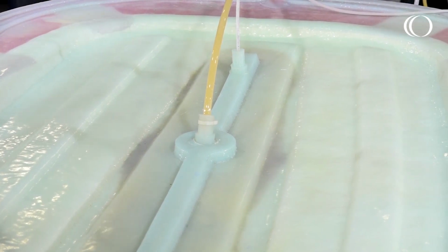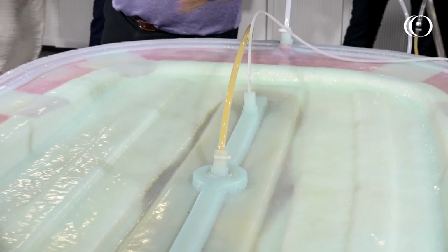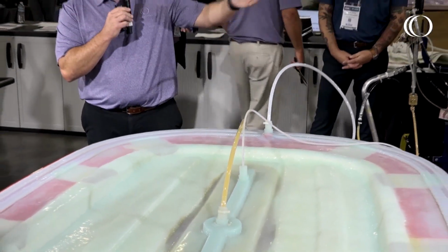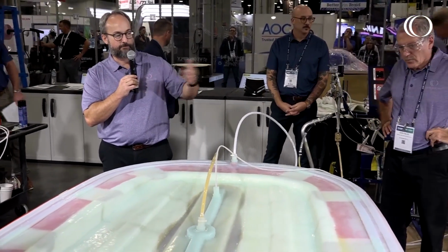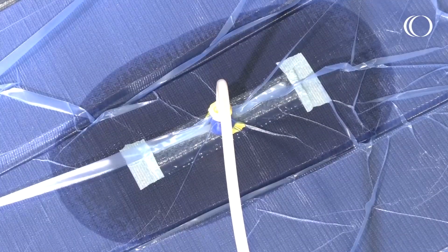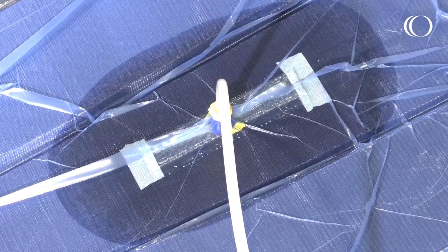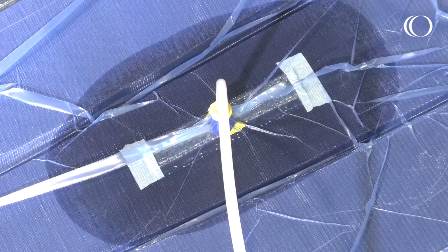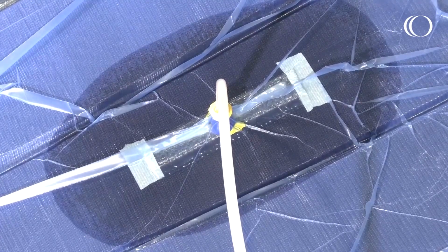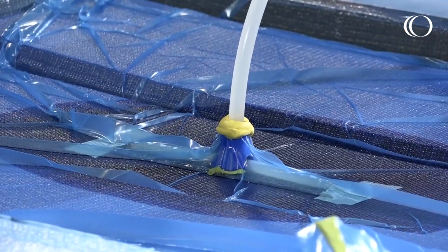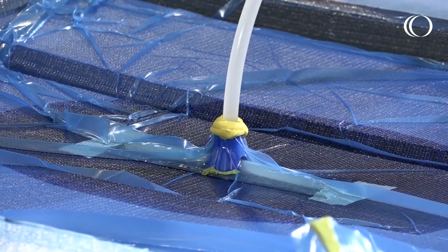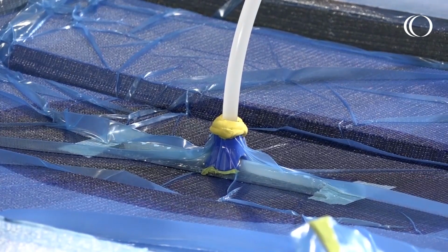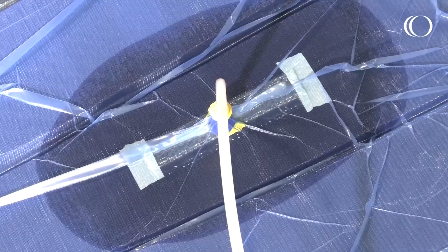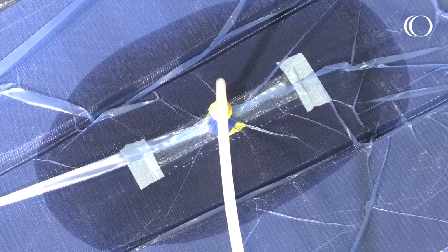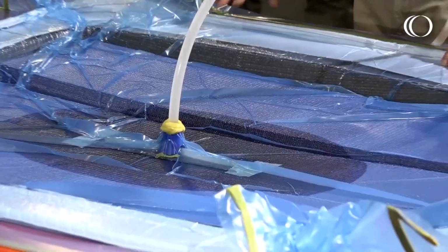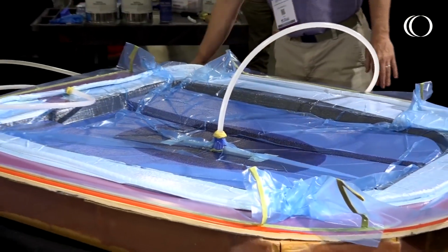The reason we're filling from the center is we only have to flow half the distance. You can see we have a similar strategy for the carbon fiber epoxy infusion. As I mentioned, we're using different resins, different reinforcements with different permeabilities. Carbon fiber is a very small diameter fiber, so you want to infuse it a little bit slower and let those fiber bundles saturate with resin so you can get all the properties out of the laminate. The glass fibers are a much larger diameter, so you can fill them a little bit faster.